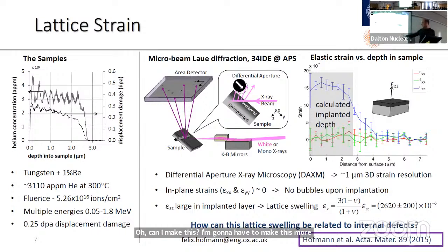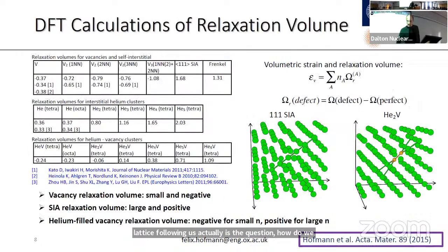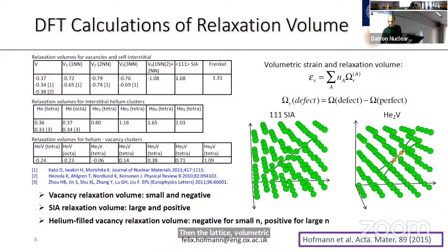So we can then go and work out what lattice swelling this actually is. The question is, how do we relate this to the underlying defects? This is where our friends from the UKAEA came in and said, well, from density functional theory, we can actually predict what the lattice strain associated with particular defects is using something called the relaxation volume of a defect. So if we can work out this relaxation volume for a specific type of defect, then the volumetric lattice strain that we get is just the number density of these defects times the relaxation volume, summed over all the different types of defects that are present.